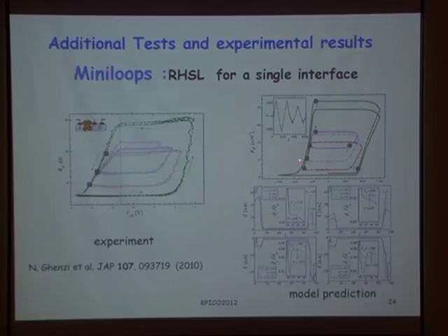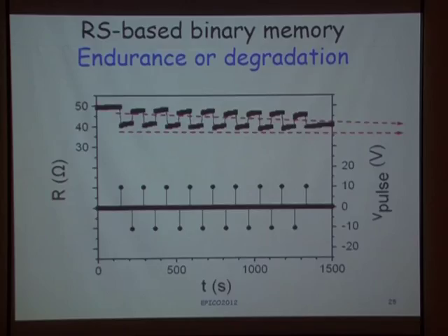voltages. And with our simulation, we have also obtained what we call mini loops. With each one of these mini loops, you can have a definite and very controlled profile of vacancies and of electric fields along your sample. So in a way, you can tailor or design different on-off ratios starting from different original voltages, and you can go through different paths.